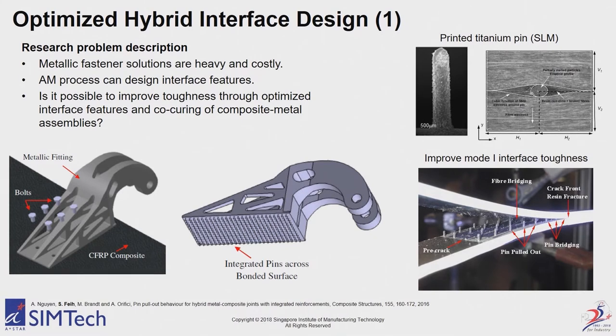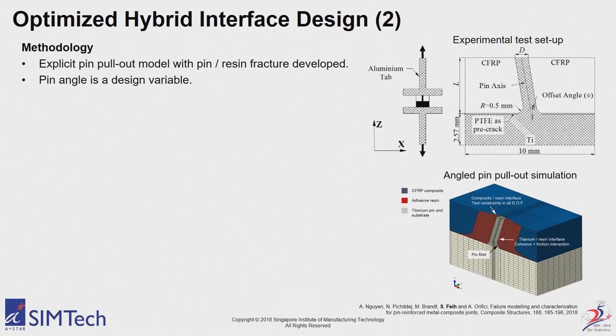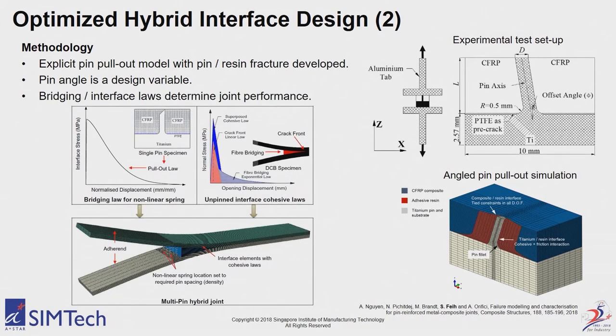And again, simulation comes to the rescue, of course, because these are things we can study with our simulation tools. So let's look at this. What we did was a lot of testing of a single pin on a metal printed at various angles, and we put a composite on top, and then we pulled the composite off. And if we do that, we get what we call a bridging law.